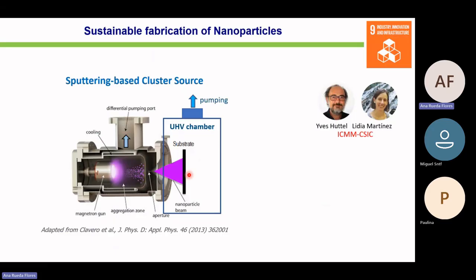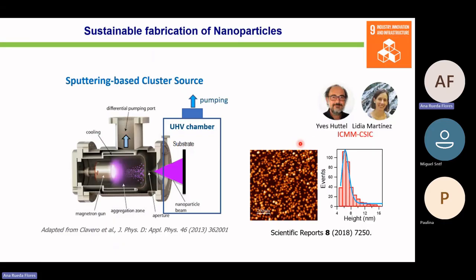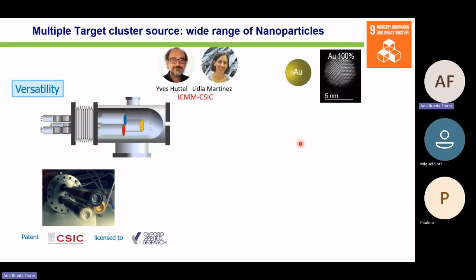This is what my colleagues at the Material Science Institute of Madrid, Yves and Lydia, have developed. And you can see that they have achieved a very good control of the size of the nanoparticles with a narrow size distribution, just with the parameters of the sputtering. And in fact, they have a patent using a multiple target cluster source. So they are able to fabricate different kinds of nanoparticles.